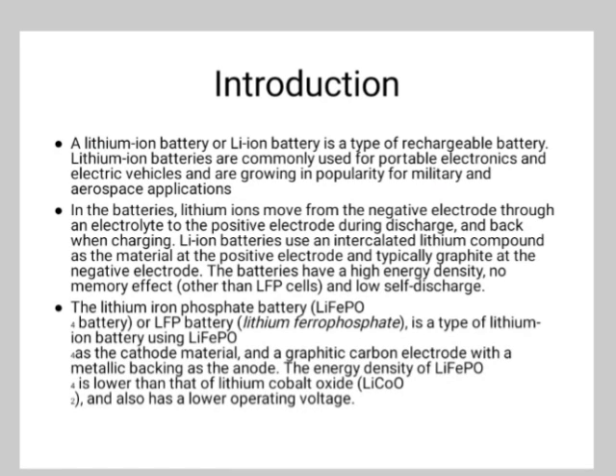These batteries have a high energy density, no memory effect, and low self-discharge. The LFP battery, that is lithium ferro phosphate, is a type of lithium-ion battery using LiFePO4 as the cathode material and a graphite carbon electrode with a metallic backing as the anode. The energy density of this battery is lower than that of the lithium cobalt oxide and also has a lower operating voltage.